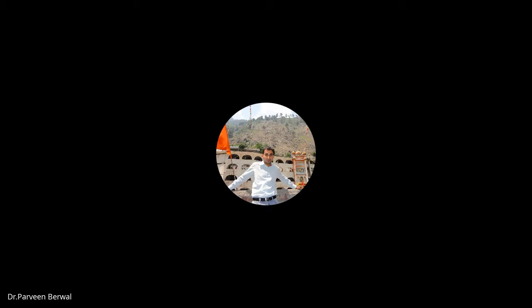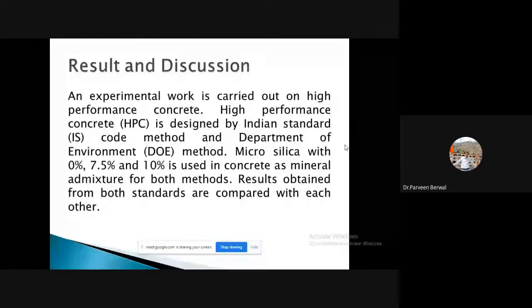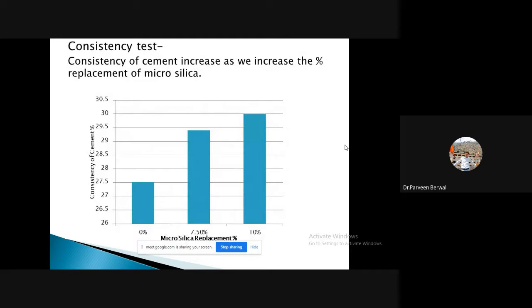Discussion part. As I mentioned, we did the replacement of 0, 7.5 and 10% on the IS method, and then compared it with the DOE method. So this is the consistency test. As you see, as the percentage of silica is increased, the consistency also increases.